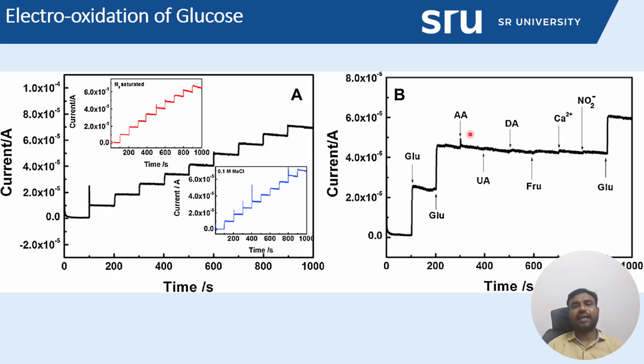It does not involve any oxidation reaction with the ascorbic acid, because the copper is highly sensitive to the oxidation of glucose. This is one of the factors. Other than that, we are applying 0.5 volt for this measured amperometric signal.